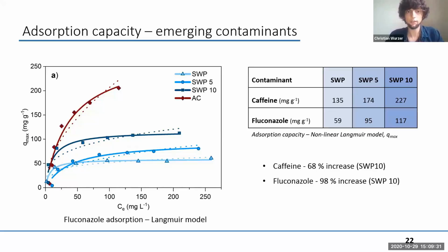In blue, the darker the blue, the more ochre content was added. And we can see we're still far off the commercial activated carbon, but more or less at 40–50% of the capacity. And what is also interesting, looking at the influence of iron addition on the adsorption capacity for biochars themselves, we see that we have between 70 and 100% increase in capacity with 5 and 10% ochre addition, which you can see on the table on the right.